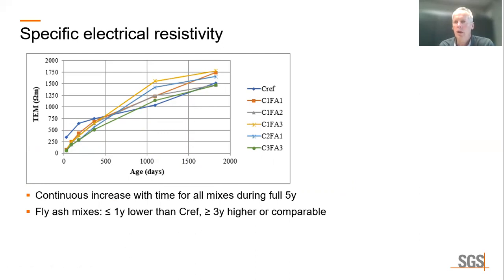And if we take a closer look at the fly ash mixes compared to the reference concrete, we see that up to 1 year, the electrical resistivity is lower for fly ash, but after 3 years, the resistivity is higher or comparable to that of the reference concrete.